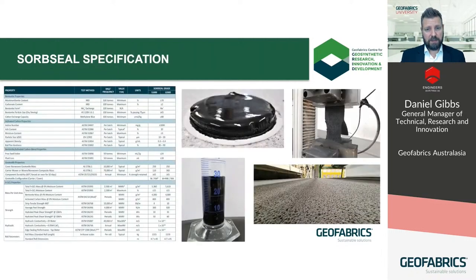And on the topic of CQA, let's take a look at the specification for Sorbseal S1000 and S2000 GCLs. As I mentioned earlier, we purposely preserved most of the well-known properties of the Alkoseal GCL range in terms of the bentonite properties, the synthetic component masses, free swell, fluid loss, of course, remain in line with industry standards. We lifted the mass of the S2000 to a MARV of 4,000 grams per square meter. And that's in line with our research and the S1000 product.